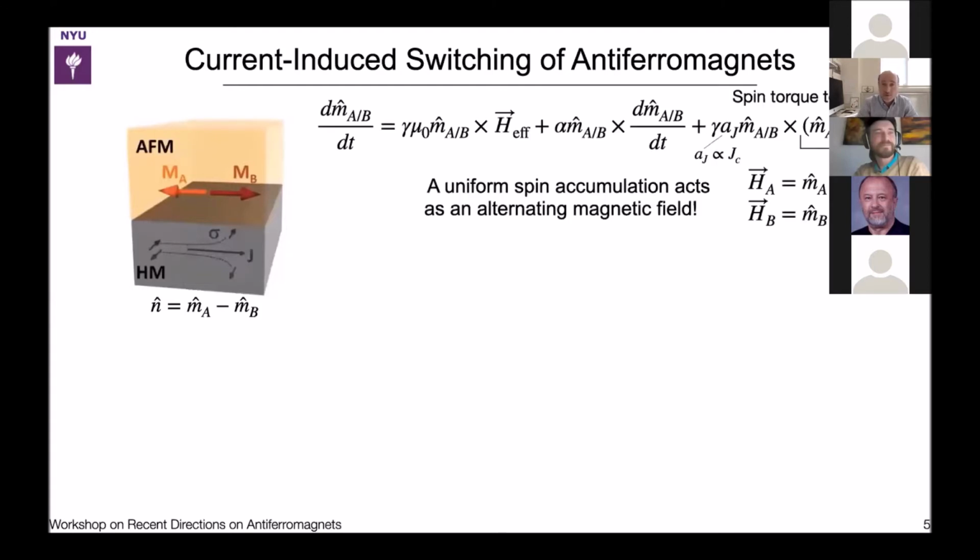But the spin-orbit torques, and also spin-orbit interactions in general, but I'm speaking mainly about torques generated by heavy metals or materials with large spin-orbit coupling that are in contact with antiferromagnets, have a quite interesting form: polarization crossed into the sublattice moments, which means that this torque or field alternates on different lattice sites.